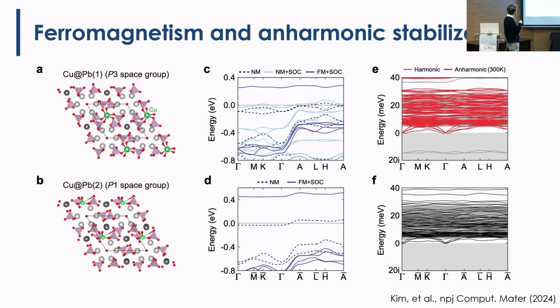And also here, the band structures, as you can see, so basically when they were doing it assuming ferromagnetism and spin-orbit coupling, somehow the system was an insulator, okay, it has a gap, and it's ferromagnetic in the calculations that Tomeu and they did in the group. So the theoretical approach, the ab initio approach, is also consistent with the interpretation that this is ferromagnetism plus, and it's an insulator, okay. So this is a bit the story here.